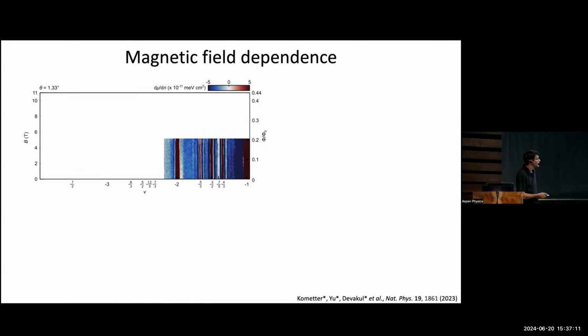All right, so what do we actually see? I'm showing here the color plot of inverse electronic compressibility as a function of hole doping, so number of holes per Moiré unit cell, and applied magnetic field, locally at some spot that has a twist angle of 1.33 degrees. In this picture, red corresponds to incompressible. That means that there's some energy gap in the system. And you can see at low magnetic fields and at low fillings between 1 and 2 holes per Moiré unit cell, there are a number of red features appearing in the data. There are these in the middle that have some fractional values. So these correspond exactly to the generalized Wigner crystals that I was showing you earlier. You have some commensurate arrangement of charge in your Moiré lattice that doesn't completely fill every single site.